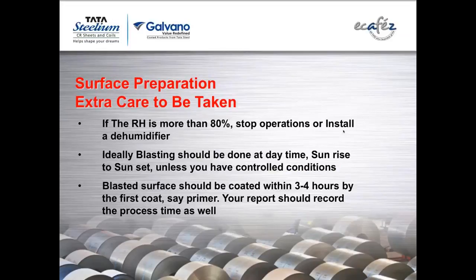A few more things, extra care. One is, if the relative humidity is more than 80%, stop operations. You are not supposed to blast, or have controlled conditions, installing a dehumidifier or things like that. Ideally, blasting should be done in daytime, sunrise to sunset, where you are outside, but inside the plants you can definitely have controlled conditions. Then there is no issue. But outside, if somebody is working near the seashore, especially in the dockyards, by 4, 4:30, 5 in the evening, they stop blasting. Whatever is blasted, they put a primer on and then keep it for the next day.